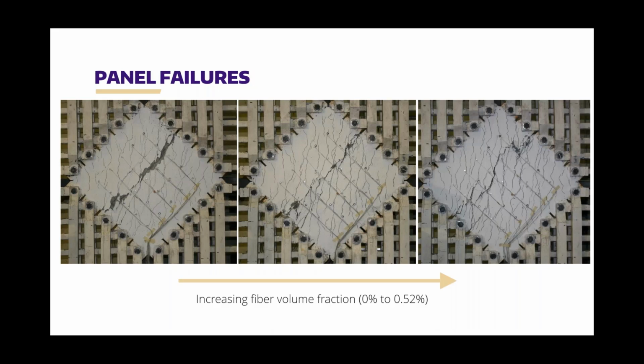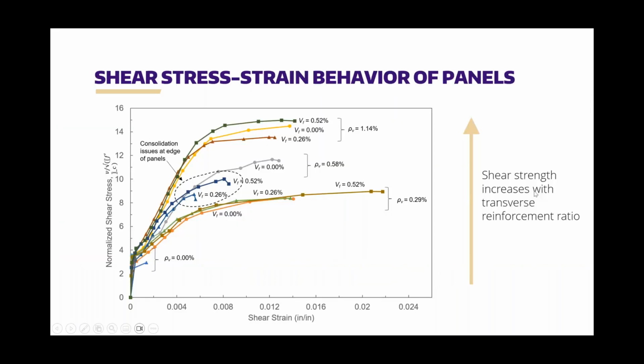And so I just wanted to show you a picture of some of these failures. So the panel on the left has no fibers. The panel on the right has the 0.52% fibers. And as you'd expect, one of the things that you can notice is that there is just a better distribution of cracking in the panels with fibers than without. So we are having fibers that are bridging those cracks and are allowing you to form those additional cracks.